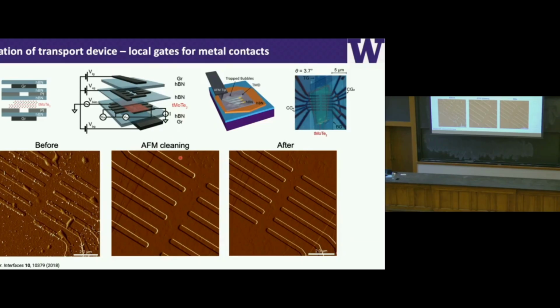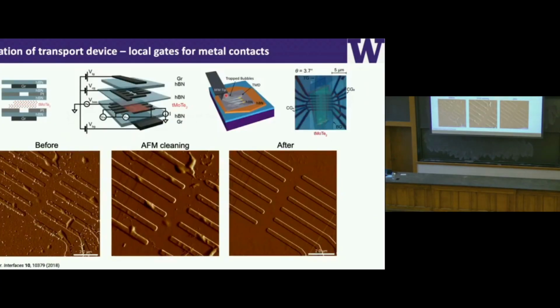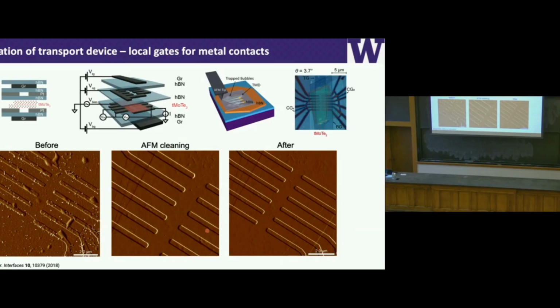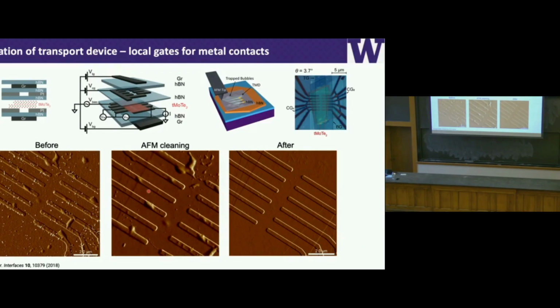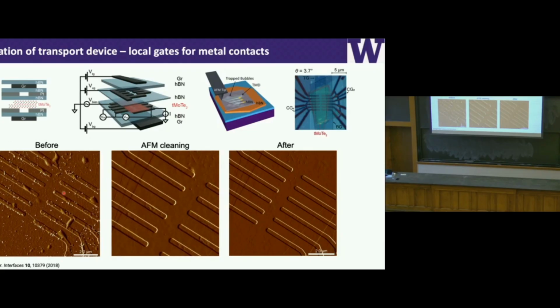The second thing we did is for every step, we do this AFM cleaning, okay? So you can see that, right? This AFM cleaning usually takes about 10 hours. It's a movie, but it takes more than 10 hours. This process actually can clean the surface, okay? And the end result, right? Initially, you see a lot of bubbles on the surface, but once we do the cleaning, the device looks quite smooth. So that's how we make a good contact and make a good device.